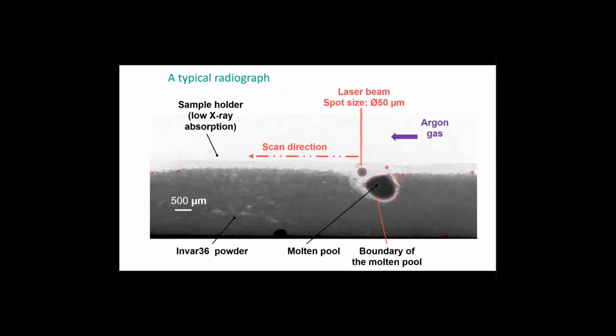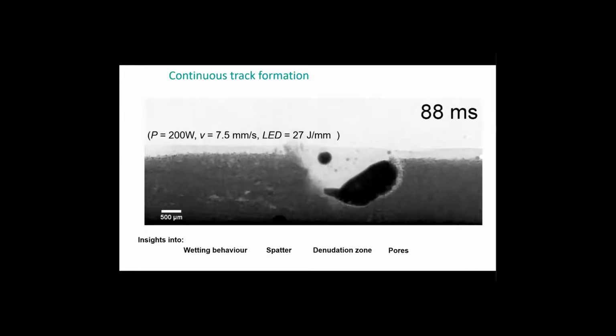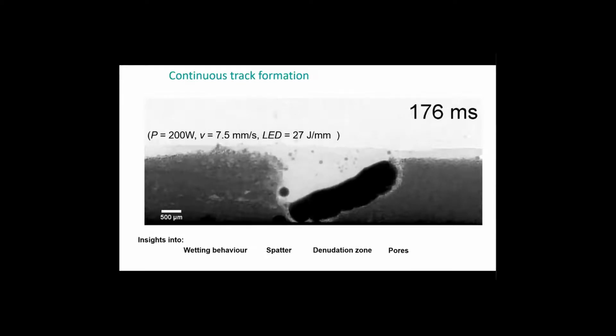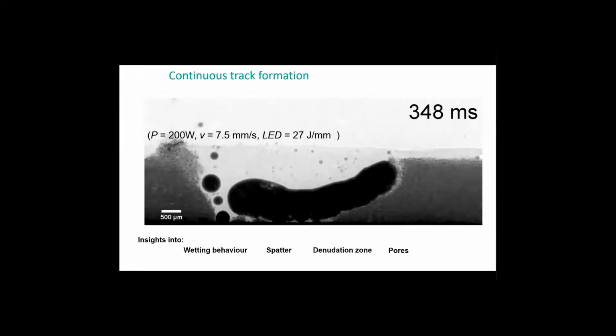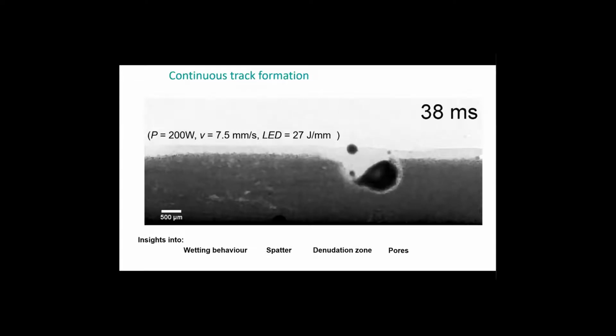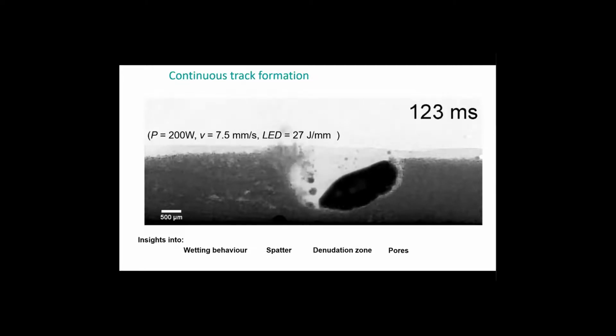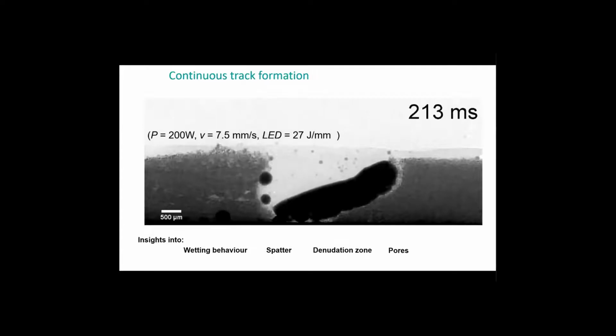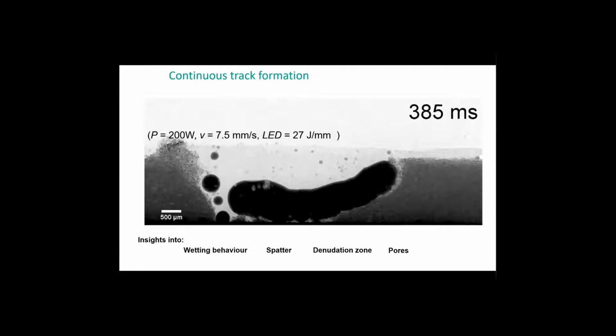So just again to show the kind of things that you can see, I think these samples tend to show the melt pool slightly differently from the last talk, but the basic technique is just the same. Here you can see the molten pool, you can see the powder, and the laser beam is moving from the right to the left. And you can see the kinds of images that show the extension of the melt pool. You can see spatter of powder particles. You can see entrained gas bubbles. So you can see many aspects of additive manufacturing that threaten the integrity of manufactured parts. And you can understand how control of the laser power, the translate velocity, the powder size, and various other aspects can be used to control the quality of the additively manufactured part.